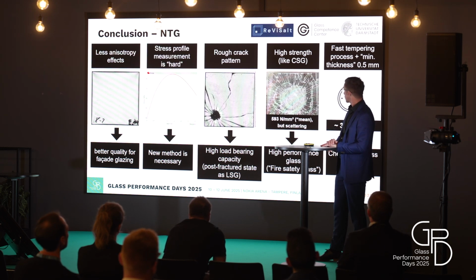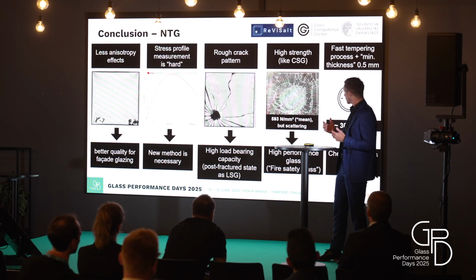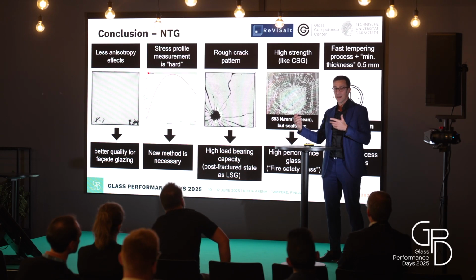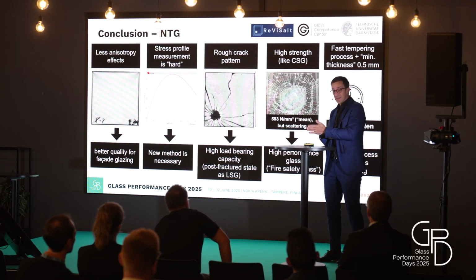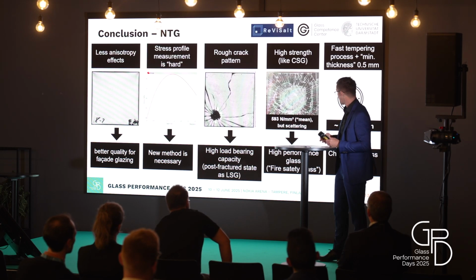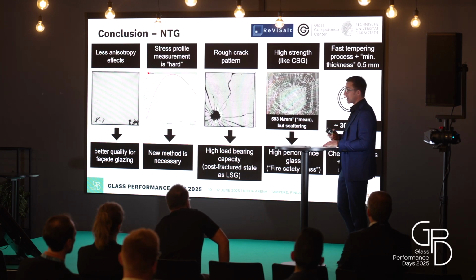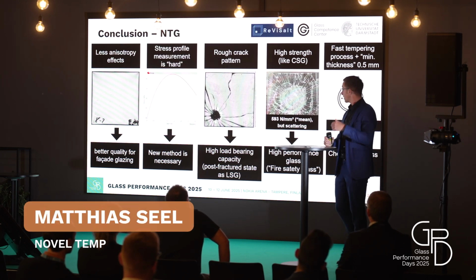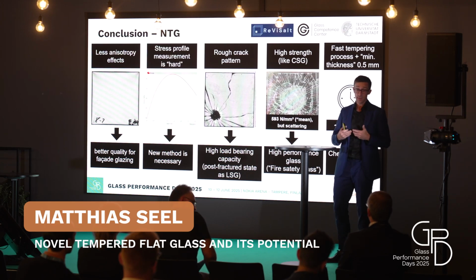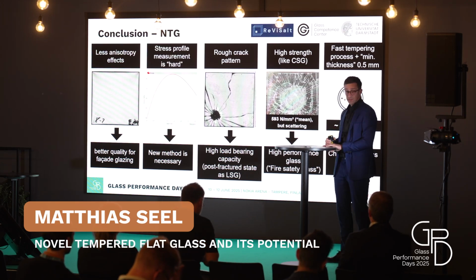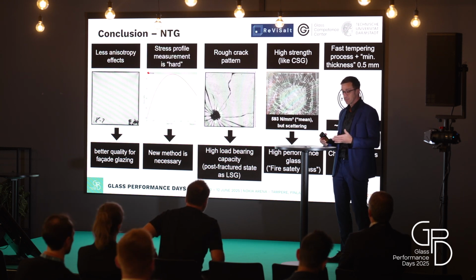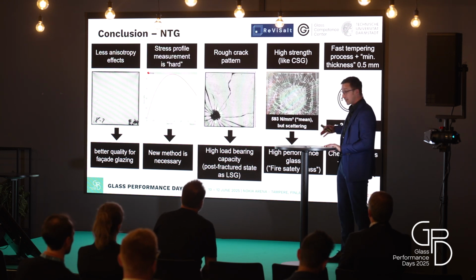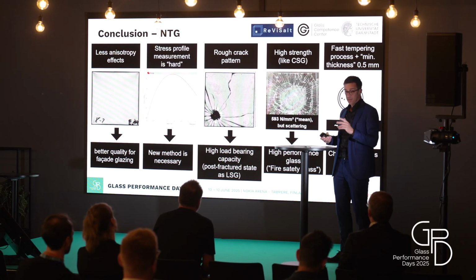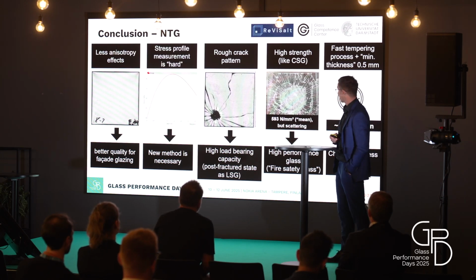We had very high strengths, like for the chemically strengthened glass. So we can produce also high-performance glass for fire safety. We can substitute borosilicate glass because the thermal shock resistance is also very high. And the process takes not many hours, only 30 minutes. It's also very fast. And so if it's fast, we can do it also as a cheap process. And it's also possible, we conduct the tests now, that we can do this for thin glass, not only for the minimum 2 millimeter or something like this.